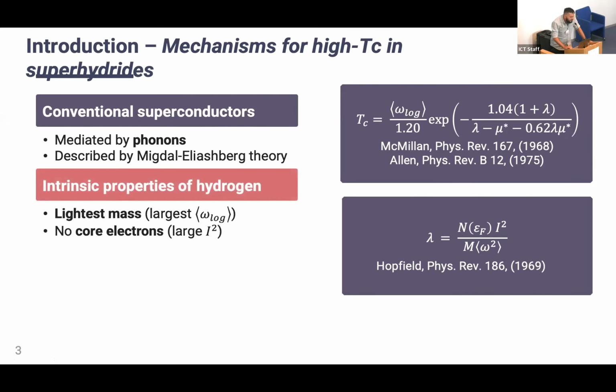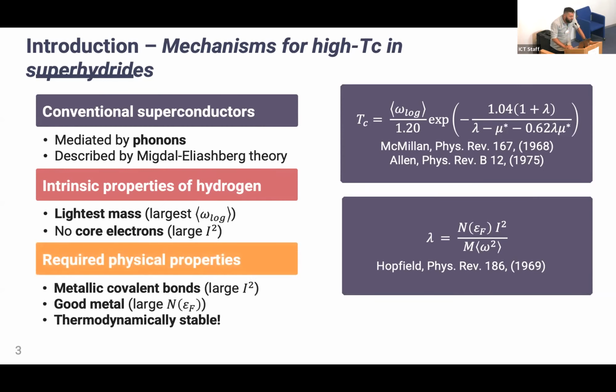So the first reason why we like to have a lot of hydrogen is, of course, it's the lightest element. So in this formula for TC, we see that the average phonon frequency appears as a prefactor. So we have a light element, we maximize the phonon frequency, we're happy. The other reason why hydrogen is good is because it has no core electrons. So that means that the ion-electron potential cannot be screened by core electrons. This boosts our electron-phonon matrix element.